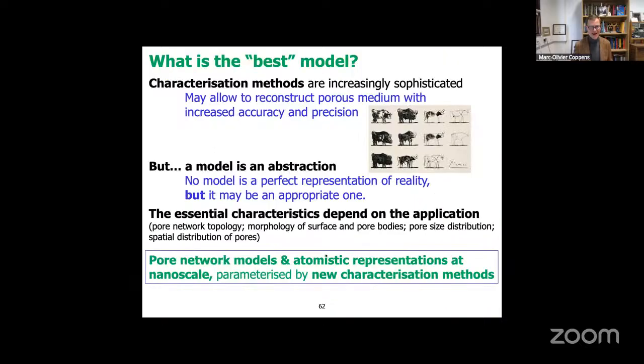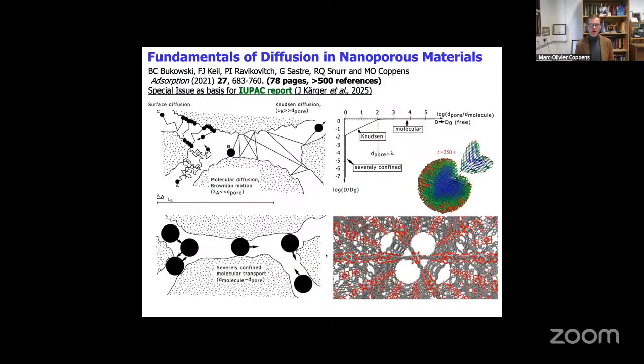Well, are they perfect, right? So that is actually a good question. I'll show you some examples where you have good agreement. There are other cases where there are factors that are unclear. So sometimes you might even get agreement, but it's just because you model it with a fudge factor. You put in a tortuosity, and it might seem good enough because if you look at this diagram here between molecular, Knudsen and the severely confined, say in a zeolite, you have orders of magnitude difference of diffusivity. So there you clearly can't get away with it.